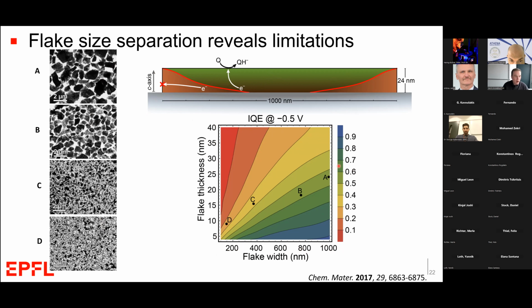Now, clearly from this, we want to achieve nanoflakes that have very large lateral dimensions and very thin thickness, only a few atomic layers, to achieve the highest quantum efficiencies. However, the sonication-based exfoliation that we use always gives us flakes that live along this line. That's due to a basic mechanical relationship between the Young's modulus of the material in the A direction and the C direction, which causes a fracture of the flakes during this ultrasonic exfoliation. So we're not able to achieve very large flakes that are very thin. If we could do that, we would expect to achieve higher conversion efficiencies.